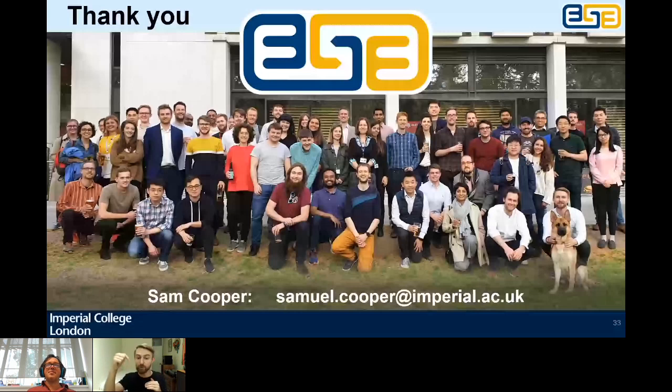And is a uniform tortuosity factor even the target anyway, right? Maybe you want to have very high surface area, dense small paths at the bottom, and maybe you want to have some nice super highways for transport near the top, right? It's not trivial still what the ideal microstructure looks like, but I think this metric will allow us to explore the optimization space in a much more instructive way.